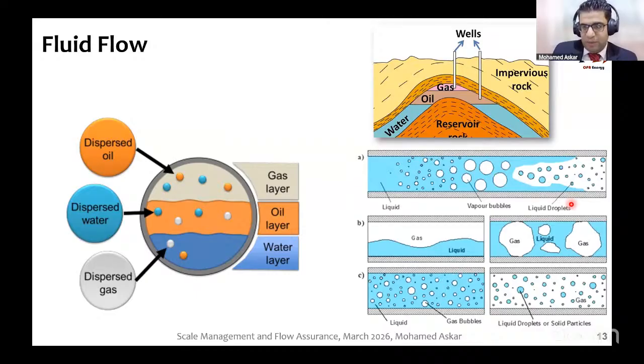But you should make sure that from the beginning, you will produce many fluids, so it will be multi-phase flow, and you should care about the interaction between these phases, because oil and water may promote some emulsion, right? Oil itself may deposit paraffin and asphaltene. Water itself may deposit scales. Gas with water may form hydrate, right? Gas and liquid may form foam. So all of these issues are flow assurance challenges. And also the water, if it has a low pH and a high salinity, it will be corrosive water, and it can cause corrosion of the pipeline.